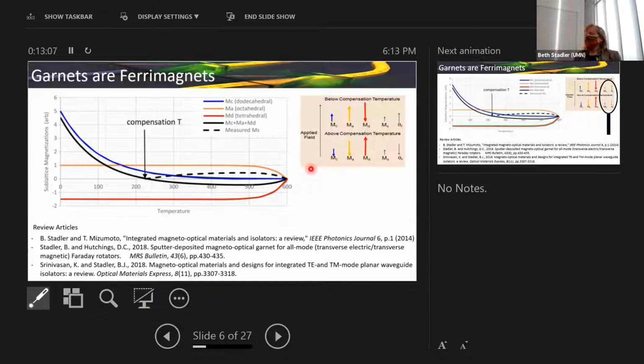The other thing that matters is you can vary this thing called a compensation temperature. This is looking at those sublattices. The blue is the dodecahedral. If your rare earth is magnetic - yttrium, for example, is not magnetic, lanthanum's not - but terbium or gadolinium or most of the others have some magnetization to them, their moment versus temperature looks like this. And if you have iron, at most temperatures, iron's either all up or all down. It turns out your iron sublattices are antiferromagnetically coupled to each other.